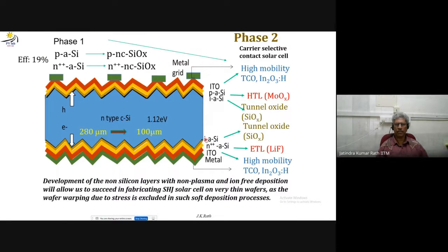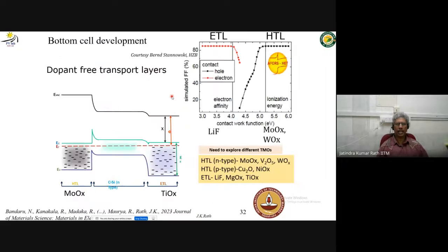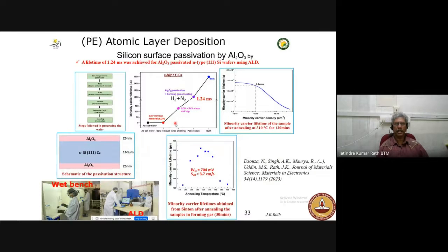One of the most important things about this sort of cell is the passivation layer, because there are dangling bonds on top of the silicon surface. They have to be passivated with some layer, and that's the trick of this sort of cell. It's called amorphous silicon. You can do that by using aluminum oxide. This is what we do, and this is the proof of the pudding.